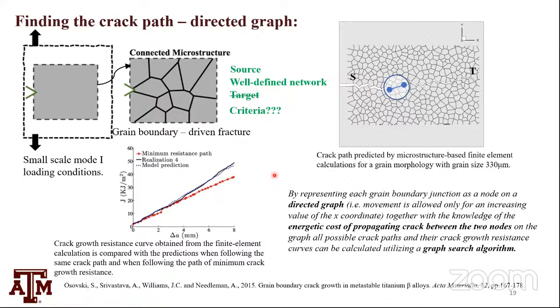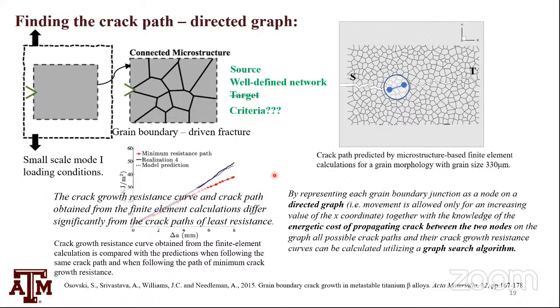And if you think about that, it makes sense because the crack doesn't know a priori where my target is. The crack doesn't know the target. It cannot minimize anything and cannot give you the path of minimum resistance. The crack follows some other criteria, which we don't know. But anyway, we found out that even if we can come up with the target, Google Maps doesn't work. So what do we do? The crack growth resistance curve and crack path differ significantly. This is the same statement that the crack path is not a path of least resistance.